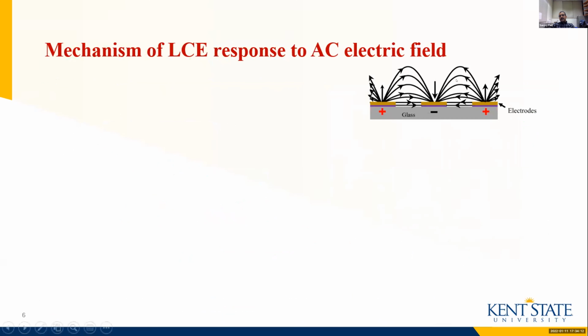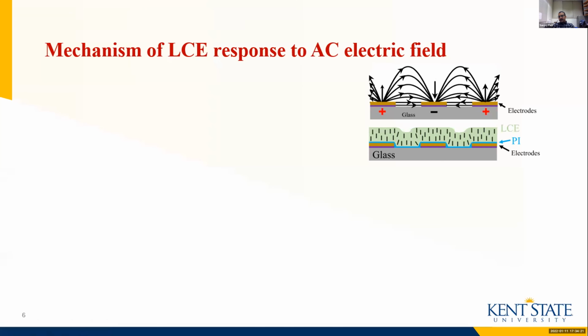So here's the mechanism of liquid crystal elastomer response to AC electric field. I present the interdigitated electrode substrate, and this is an approximate electric field distribution in it. Here's the picture of the liquid crystal elastomer coating on the interdigitated electrode substrate. We see that on the electrode region, we have a flat region, and it follows the topography of the interdigitated electrode substrate. That's why we have a valley. And these ticks here represent the liquid crystal mesogens.